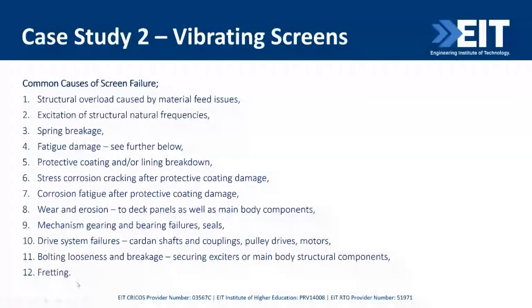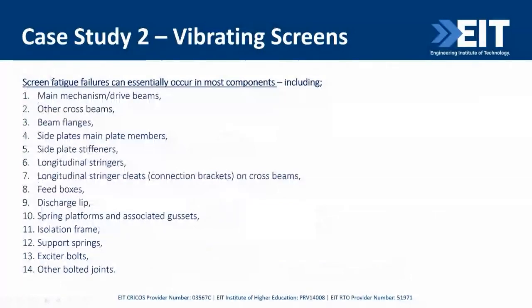So your screen failures will be everywhere. Springs, material feed. Material feed to get right is critical. When you see a coal washery plant with a large lump of coal coming down the conveyor into the feed tube into the screen, the size of a fridge, you know you've got a problem, and it's got to be rectified. Because that's not fatigue, that's overload impact in one fell swoop. Fatigue damage can happen anywhere. Those main drive mech beams and the exciter bolts, your cross beams that hold the longitudinal stringers that hold the deck up, your cleats to hold the stringers, anywhere and everywhere if it's not set up properly.